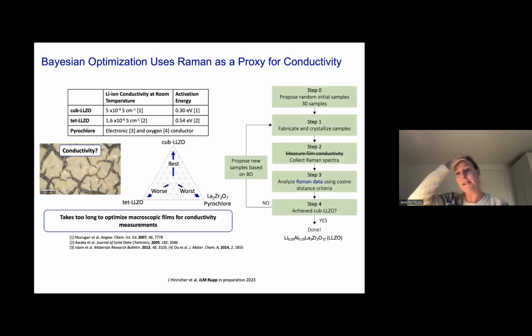So here's one example that I just want to highlight. We looked into the class of lithium garnet, and I showed you before that what we want to have is the cubic lithium garnet phase, right? So we don't want to have the low conducting tetragonal phase, or the underlithiated or non-lithiated pyrochlore phase, because those would be much worse. That's indicating a drop in the lithium conductivity. Then there are other parameters that come into play when you process, right? So we want to have nice, dense, smooth films like I showed you before. There are also some films that, if you overshoot temperature, will look a little bit like the desert, when you get mud cracks. That's what you don't want to have. It's not a solidified film.